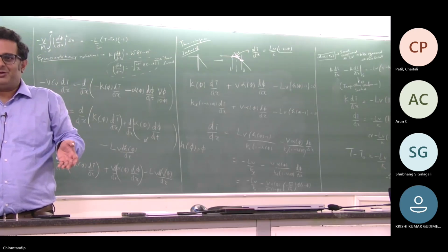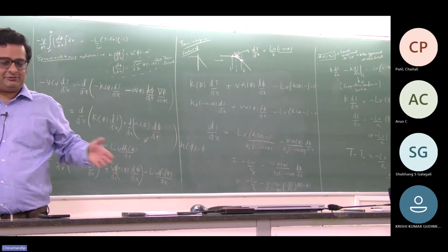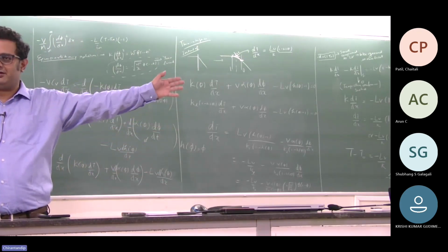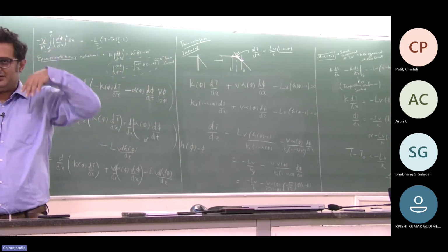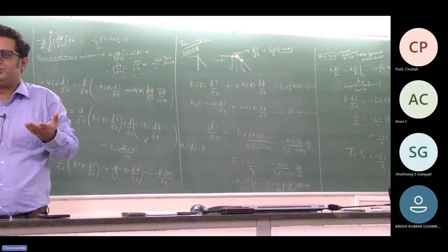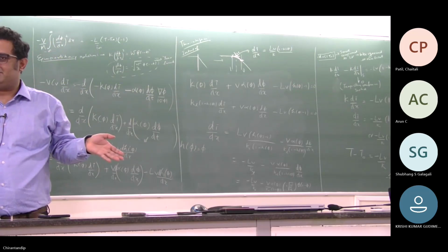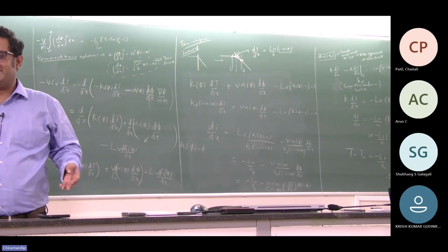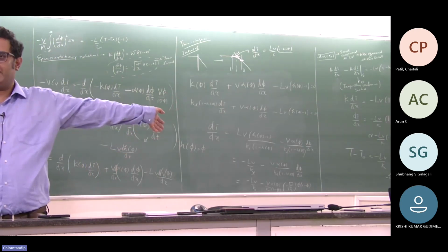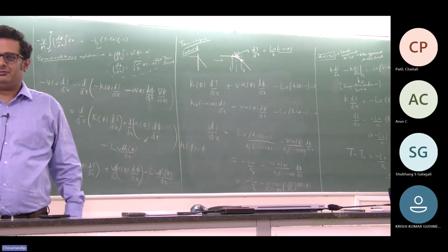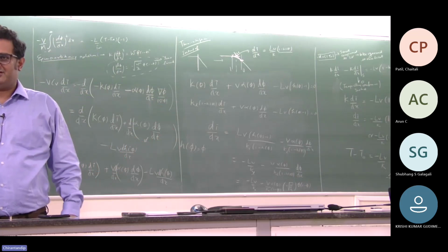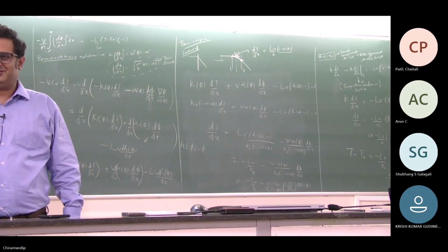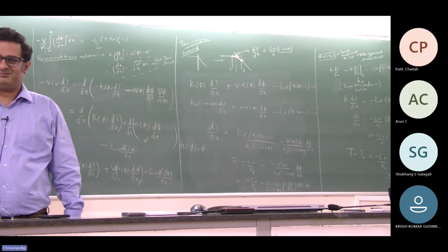But that's not a problem, because for me the interface is a creation. I am basically worried about what my bulk solution, which is far away from the interface, is seeing at the interface asymptote. What if my asymptote is seeing the right value? My sharp interface description will convey that the asymptote value must be TM, or if beta is 0, it should be TM. If it is Li, it should be CL or CS equilibrium. So it depends on what you're talking about. It's the asymptote value; we don't care what's at the actual interface. The asymptote value must be the same, conveyed with the sharp interface.